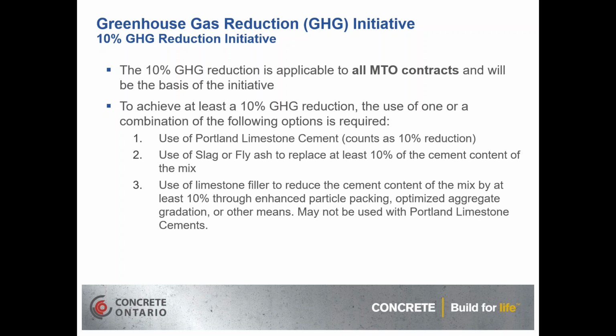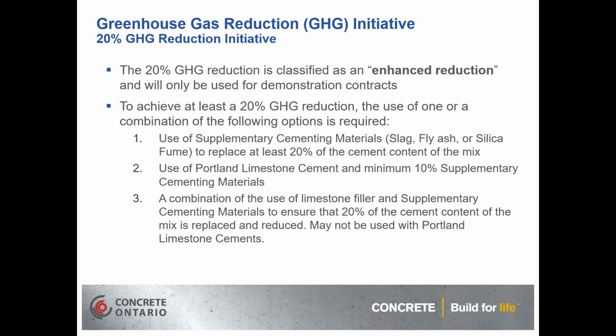And the third option is the use of a limestone filler to reduce the cement content of the mix by at least 10% through the enhanced particle packing and optimized gradations and improvements to rheology and other means. But we have to consider, again, with the limestone filler, we can't use that with the Portland limestone cements, although we can use it with the slags or fly ash to achieve the 10% or more reduction if we want.